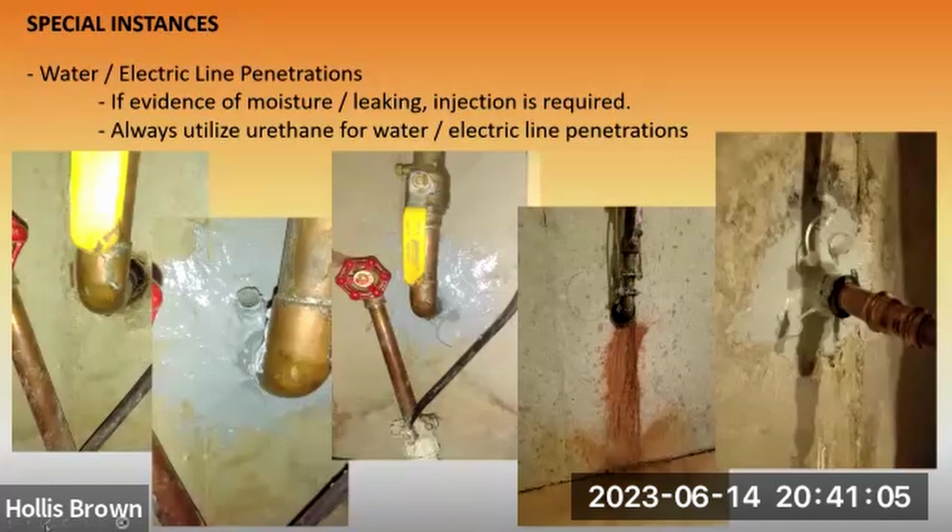I started seeing the wall below, see where that stain is? And this was up high. About that far down, the wall below just started oozing the urethane material. I thought it was like the Amityville Horror, the wall started, what the? And it's because, if you think about it, they have that 4-inch line with maybe a sleeve in the wall, and they dumped the concrete in there. They didn't get it vibrated around the bottom side. So you had basically honeycomb underneath it, but the surface looked really smooth. You couldn't see the honeycomb on the surface.